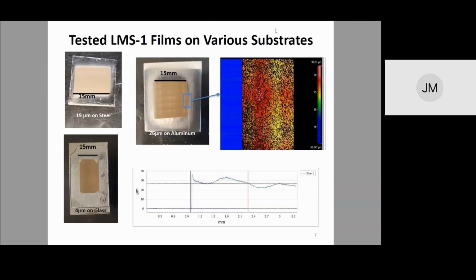These three samples are the ones that I specifically tested for this project so far. So we have a 19 micron thick film on steel on the top left. Bottom left is a 4 micron film on glass. And then the top right is a 26 micron film on aluminum.